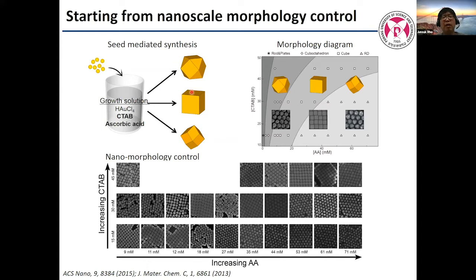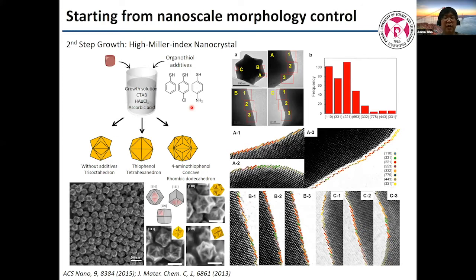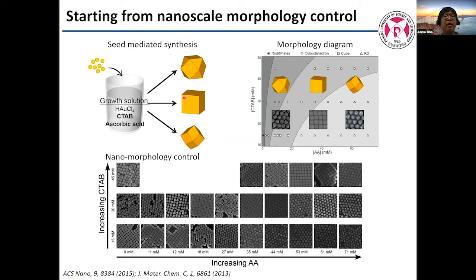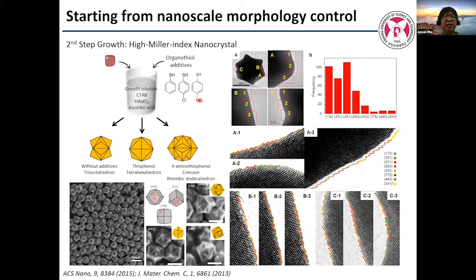But you can see they all have this symmetry, so they are not chiral, they are achiral, symmetrical structures. And then some people demonstrated this one, called high Miller index nanocrystals. They start from certain low Miller index nanocrystals, and then do a second step, hierarchical growth of this chemistry. Following a certain line, they evolve some second hierarchical structure.